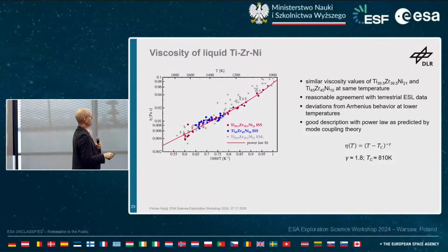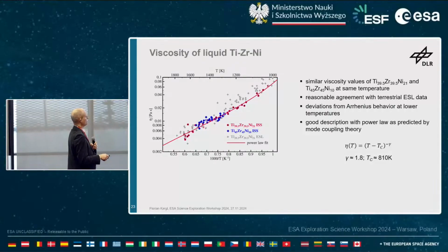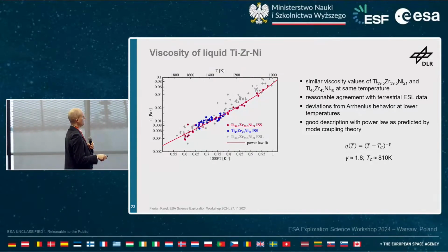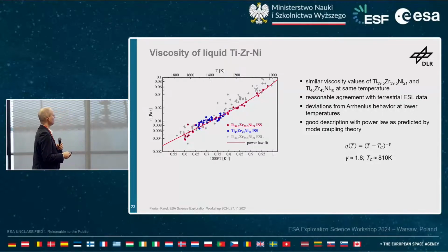And this deviation from Arrhenius behavior at lower temperatures can be understood with this power law fit, basically, which is predicted by mode coupling theory. So this is a glass forming system, should behave or should show this power law dependence. Exceptional really is here that you can very, very deeply undercool the system. And if you look at the viscosity's absolute values, it's not changing an awful lot. So you have 800 degrees and it's only an order of magnitude change in viscosity. Still relatively low in viscosity.